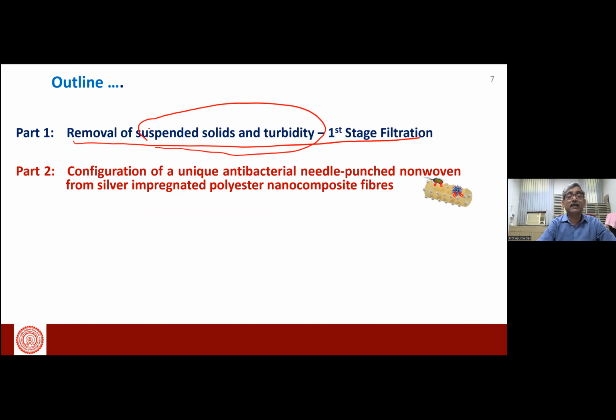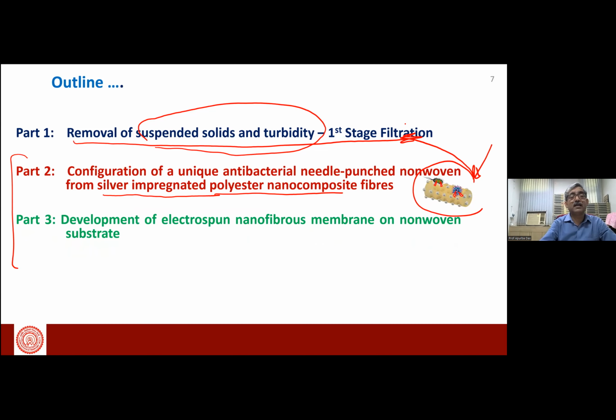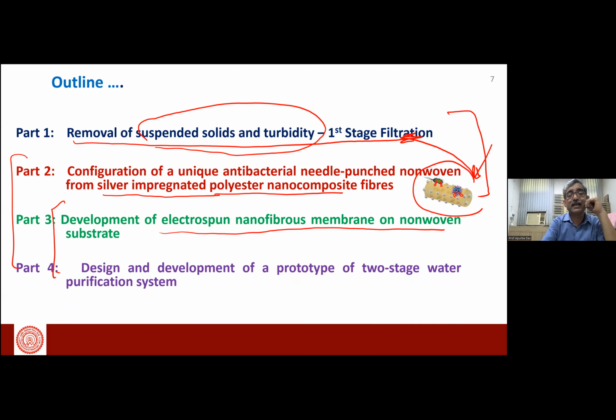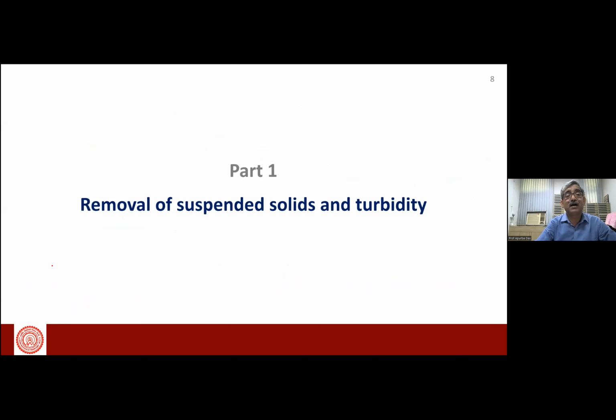Then in the next stage, we have tried to incorporate nanotechnology. Polyester fibers impregnated with silver nanoparticles are available, so we have used this fiber in the non-woven fabric manufacturing. Then came the development of electrospun nanofibrous material. After preparing the non-woven fabric, we used the electrospun nanofibrous membrane on the non-woven substrate, and then the design and development of a prototype water purification system. These are the stages we have covered.